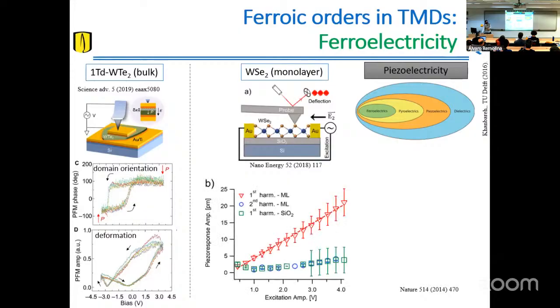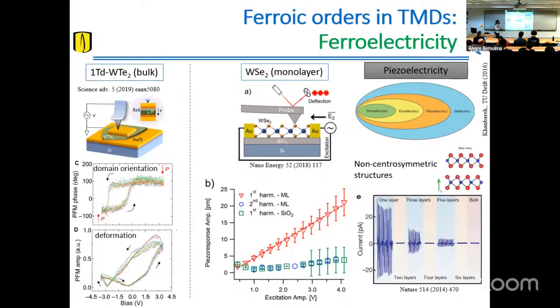More commonly, these piezoelectric and ferroelectric effects have been reported in nanolayers and monolayers of, for example, tungsten diselenide. We can measure the amplitude of deformation as a function of voltage and define a piezoelectric coefficient, which is the response of the material through deformation under an electric field. This behavior is not hysteretic, it's only piezoelectric, so the material is not ferroelectric, but it points to the formation of some polar domains in the material. And this big response happens only in an odd number of layers of the material, which